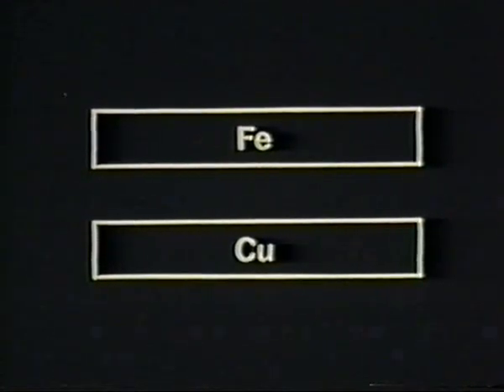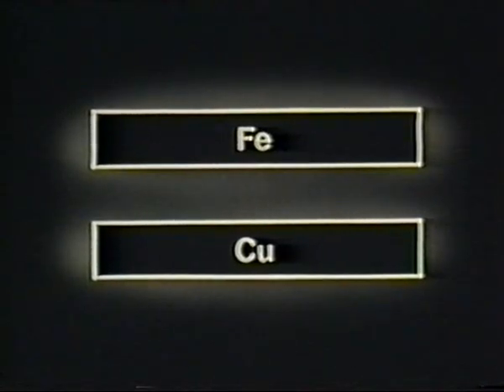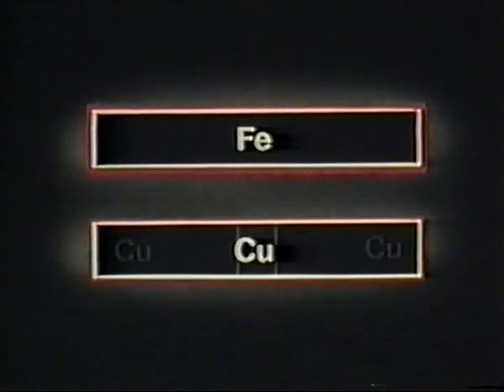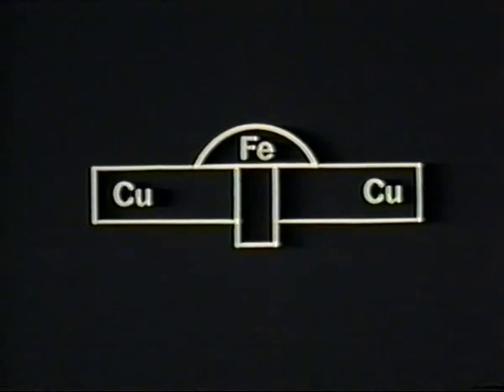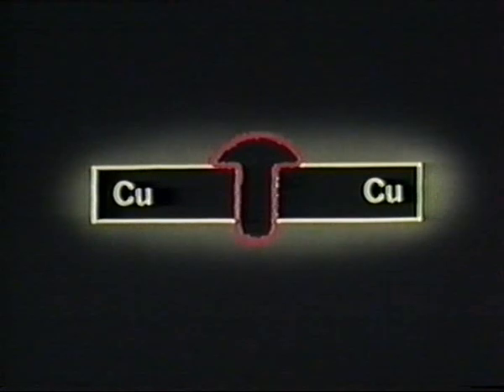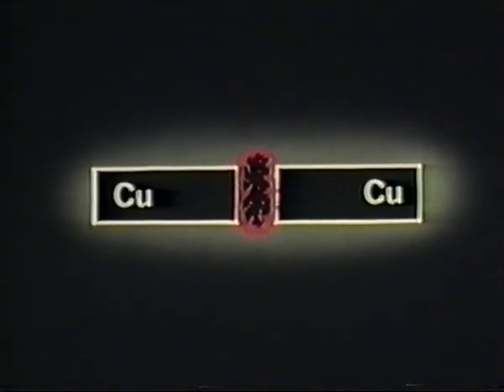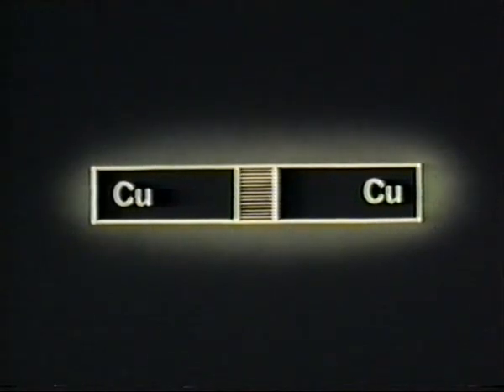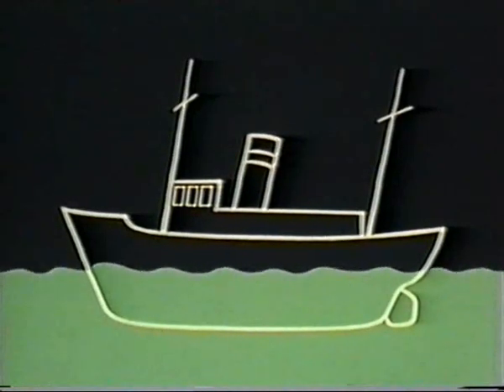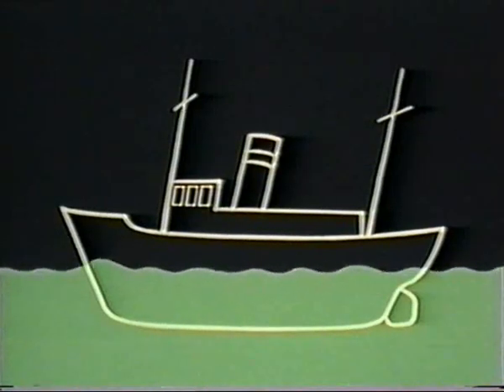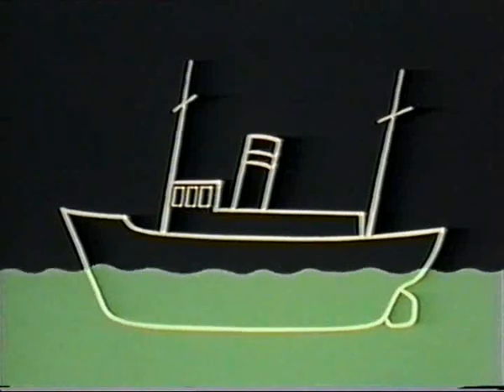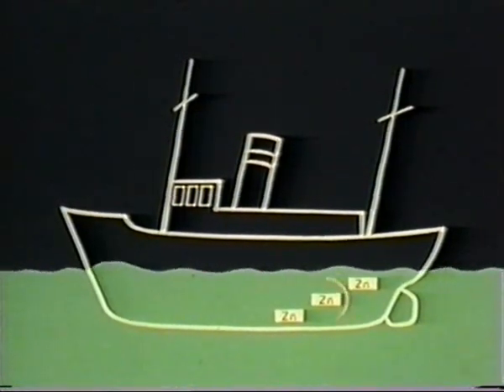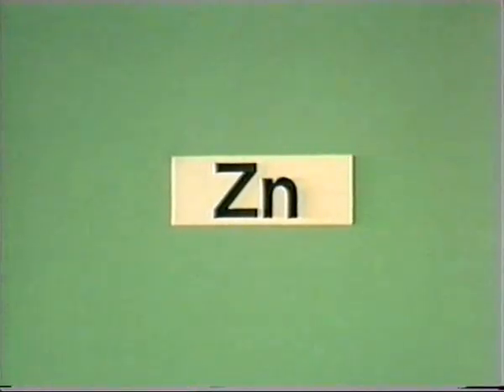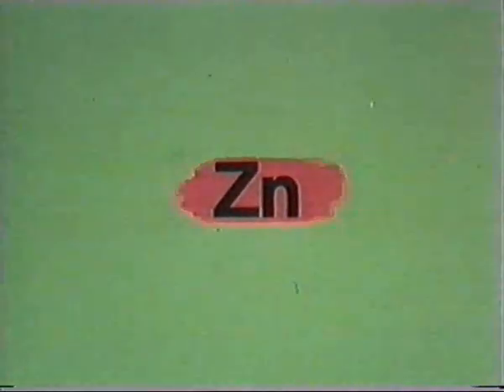We have seen that when metals are placed in an electrolyte, such as seawater or wet earth, each of them may corrode. However, when the two dissimilar metals are brought into direct contact with each other and immersed in an electrolyte, the corrosion of the steel will be accelerated. But at the same time, the copper will have been protected. This reaction is turned to advantage in cathodic protection, used, for example, on underground pipes and ships. On its own, the steel hull would corrode in seawater where paint had been damaged. So, zinc blocks are fitted in good electrical contact with the steel. The steel is protected and the zinc corrodes. With zinc blocks fitted in the right places, the hull remains intact as long as the zinc is replaced regularly.